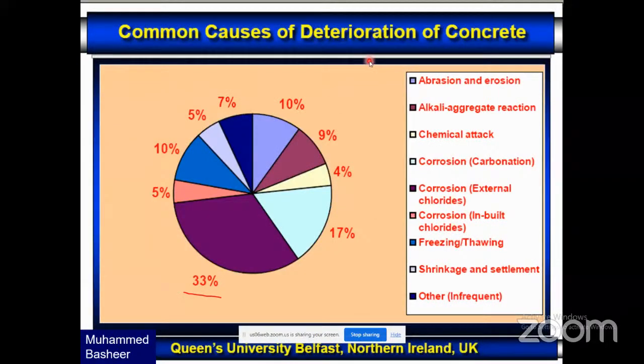So what is the common cause of the deterioration of materials? Sometimes we are not so aware. This is from Professor Basheer, UK. Based on the findings, about 33 percent, the major contribution, is due to corrosion effects. The external chlorides would induce the deterioration, and the rest were mainly contributed by the shrinkage effects, then corrosion due to carbonation, alkali aggregate reactions, abrasion and erosion.